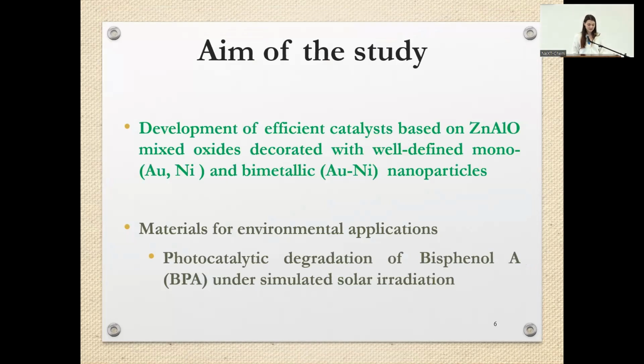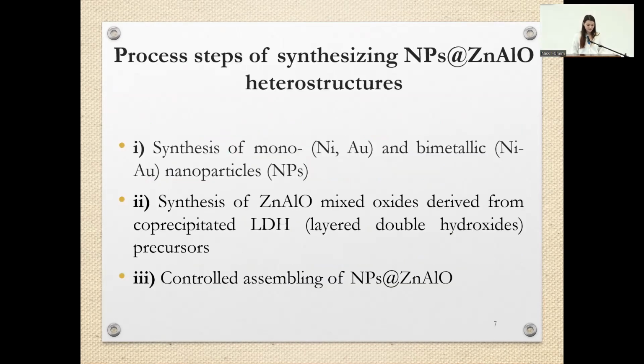The aim of the study consists of the development of efficient catalysts based on zinc-aluminum mixed oxides decorated with well-defined mono and bimetallic gold-nickel nanoparticles, and to synthesize materials for environmental applications, more specifically photocatalytic degradation of bisphenol A under simulated solar irradiation. The process of synthesizing nanoparticles on the zinc aluminum oxide heterostructure consists of 3 distinct steps.